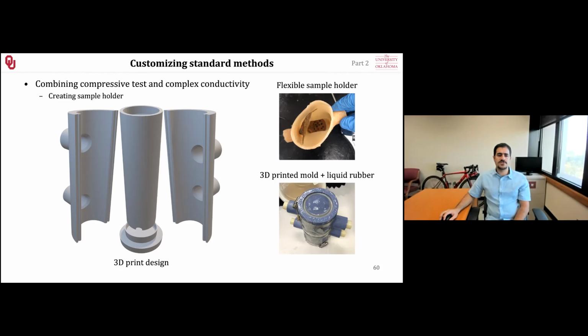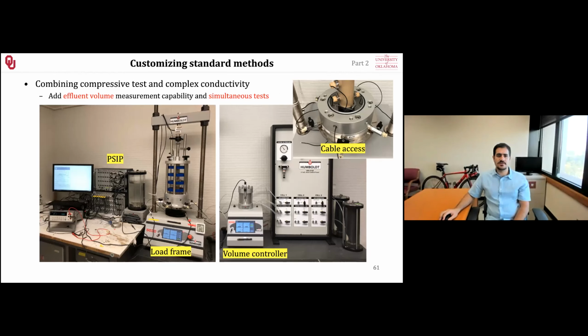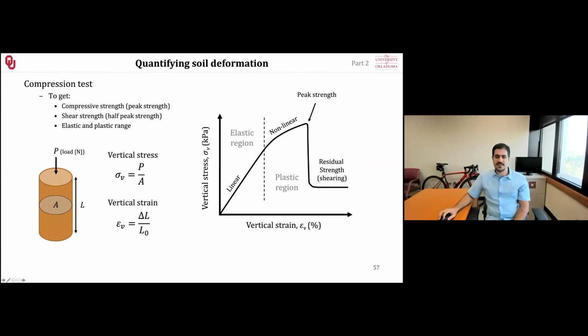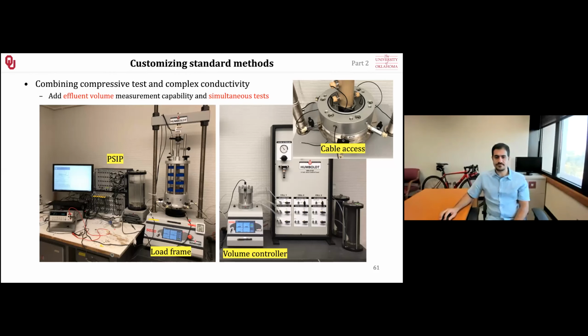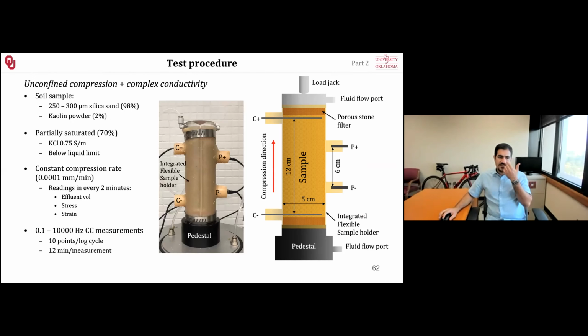It allowed us to combine a compressive strength test with complex conductivity. At the same time, we were measuring the SIP signal, the complex conductivity, and the compressive response. So we were measuring these simultaneously and were able to correlate the two together. Our finished sample holder looks something like this. In the civil engineering setup, we don't have these electrode holders, and it's just a uniform column.